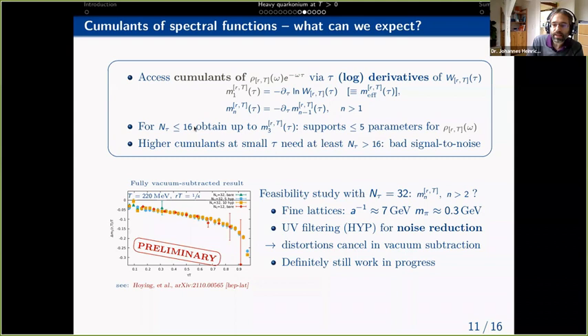So far with Nτ up to 16, we could only get signal for the first three cumulants, which means that if we include the fact that our ground state and our tail each come with a weight factor, we can sustain at most something like 5 parameters in our spectral function. And if we want to have any chance of getting higher cumulants at small times, which are interesting for understanding the properties of the state, we have to go beyond Nτ 16, where we then suffer bad signal-to-noise problems, as for example also in the transport coefficient calculations.